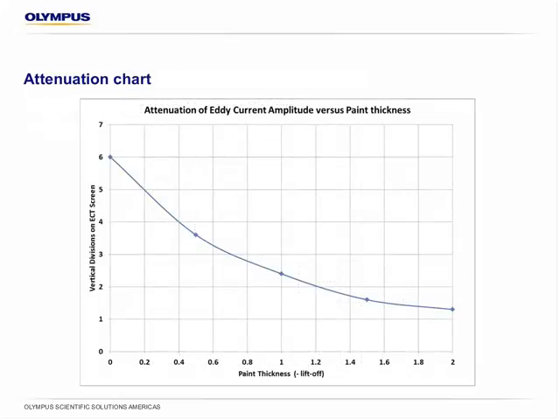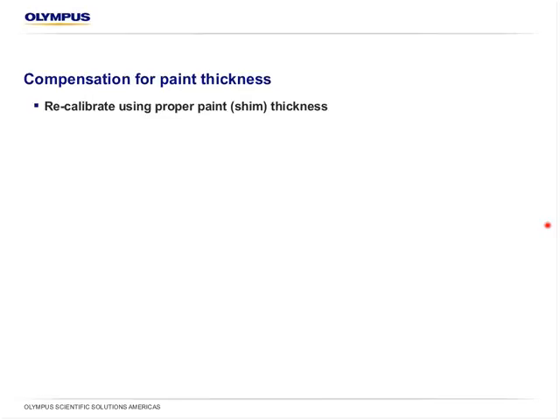So, as we plot this attenuation of the vertical amplitude in divisions against the paint thickness, we obtain an exponential decrease, which is following what the eddy current theory predicts anyway. That's not a real surprise. So what do we do? It's possible to compensate for that paint thickness in order to have a uniform sensitivity for the test, as we need to have proper detection. So it's possible to recalibrate using the proper paint or shim thickness. We use the shims in order to recalibrate and simulate paint. All we do is increase gain in order to obtain identical results.